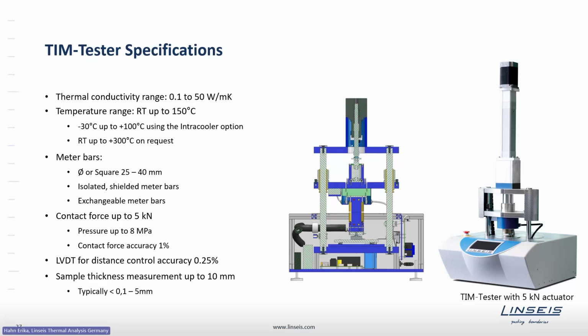Some analyses need the analysis also of a pressure dependency. This can be done using the software so that we can control the pressure with different actuators on top of the instrument. Lower or higher pressures can be realized onto the sample. With our most powerful actuator of 5 kilonewton, here you see a picture of it, we can realize a pressure of about 8 megapascal onto the sample.